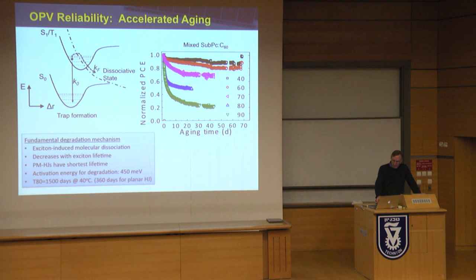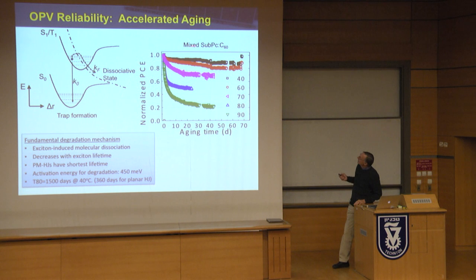We've really made a study of this for OLEDs, because there's a big problem in OLEDs. The blues are much shorter lived than the greens and reds, and that's been a problem for the display and lighting industries. And we started to look at the very fundamental processes of why OLEDs decay, and they're pretty similar to this, but now we've applied it to solar cells. And this just shows a mixed subphthalocyanine C60 cell. But basically what's happening, and you can fit the curves using basic rate equations. You have an energetic exciton that sits up in this excited state, and when it non-radiatively falls back to the ground state, it can dump all of its energy into a bond. And that bond can then dissociate. So the molecule actually goes into a dissociative state. And that's one of the primary mechanisms for these things to die.